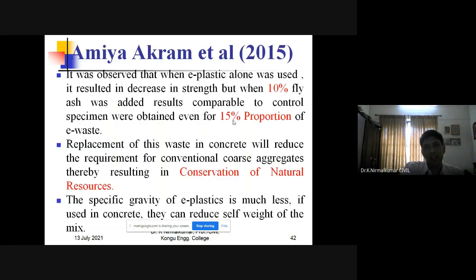I think here we are having a different scenario when we compare with Kaniyappan et al. Here, for the tensile strength, the initial days are okay. Up to 10% it is okay, but beyond 10%, even at 15%, the tensile strength is much lesser. This may be due to the materials taken by Akram et al. and Kaniyappan et al. It may be a different one. That is the main reason we are having this kind of thing. Based on these inferences, we have to choose the proper materials for the replacement.